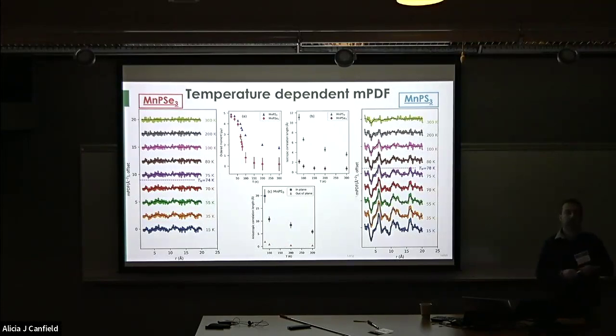You have a more limited temperature range in your correlation length plots versus your order parameter. Well, this is going below the transition. There's one point missing here. I forget why we didn't collect it there. It will be bad, but it really truly diverges. Here we're looking above the transition to look at correlation. I think it just goes to infinity, or it kind of doesn't matter what you choose because of the transition.